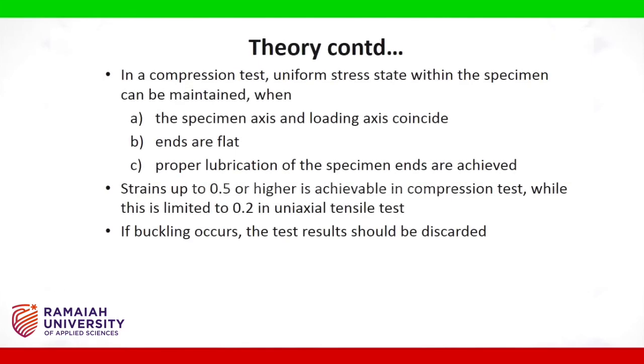In a compression test, a uniform stress state within the specimen can be maintained when the specimen axis and loading axis coincide, the ends are flat, and proper lubrication of the specimen ends is achieved. Strains up to 0.5 or higher are achievable in compression test, while this is limited to 0.2 in uniaxial tensile test. If buckling occurs, the test results should be discarded.